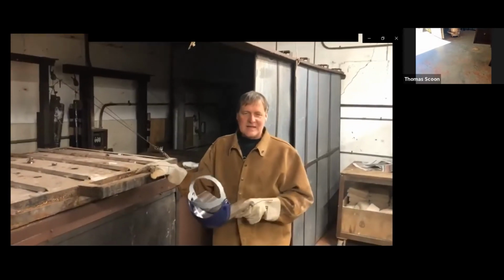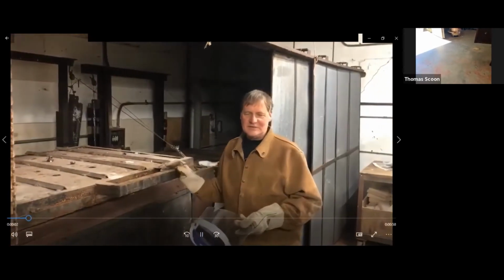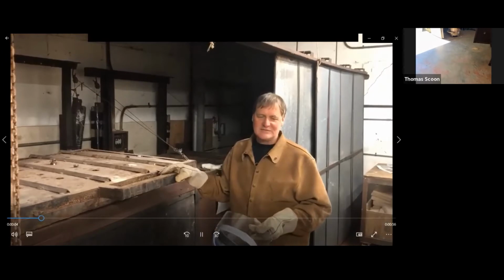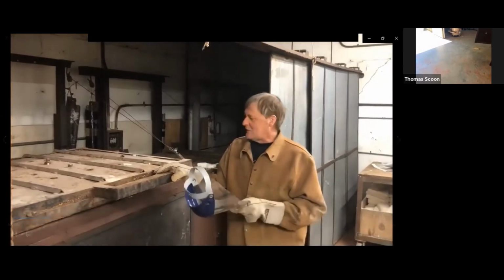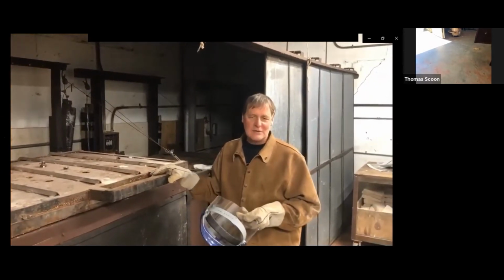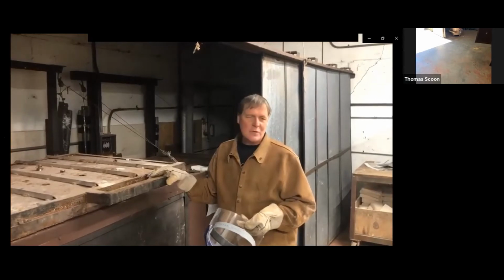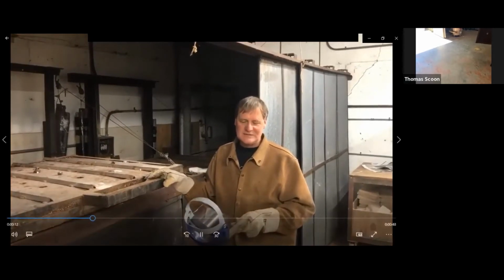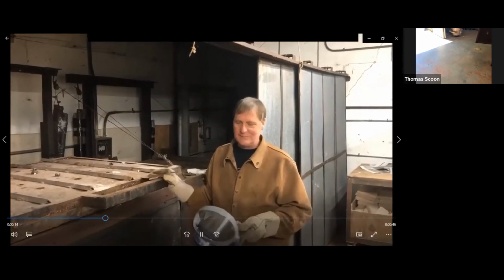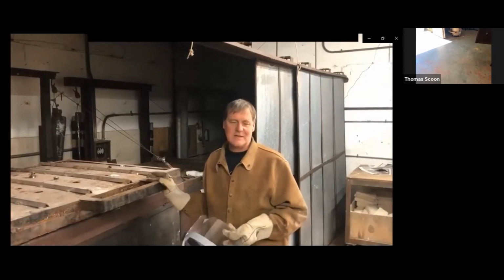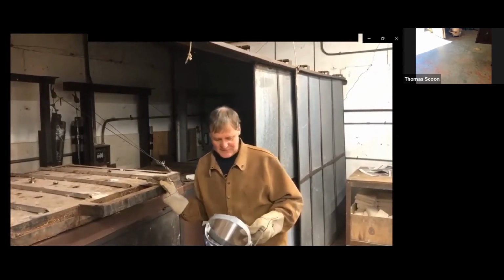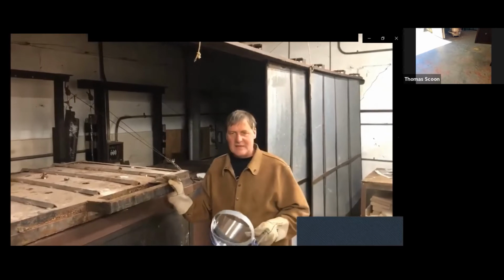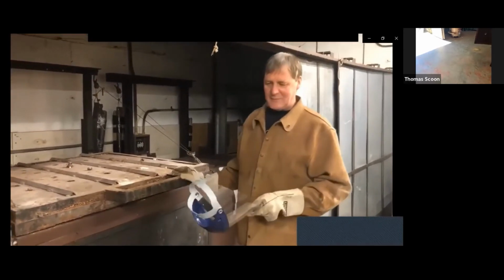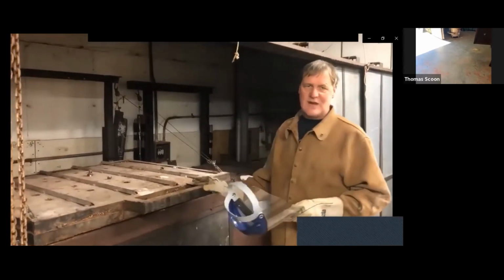This kiln is at a casting temperature of 1650 degrees. There are 2 large-scale thighs for a seated figure in here. I loaded the molds about 2 days ago. It takes about 20 hours to come to 1,000 degrees, and then you tell a computer to have the kiln go as fast as it can from 1,000 to 1,650 degrees. It hit temperature this morning, and it has been up now about 10 to 12 hours. The pieces are almost cast out right now.